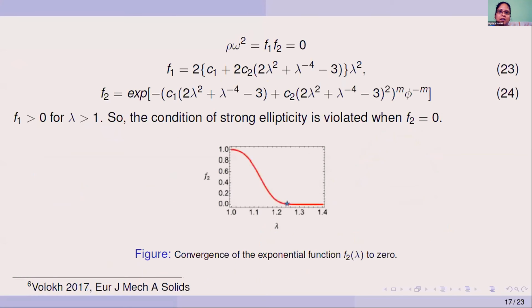these split conditions. Here F2, the exponential function, does not depend on alpha, and F1 also does not depend on alpha in case of equibiaxial tension of an isotropic material. So here we also see that this F1 is always positive under tension. So the condition of strong ellipticity is violated only when this exponential function F2 becomes 0.